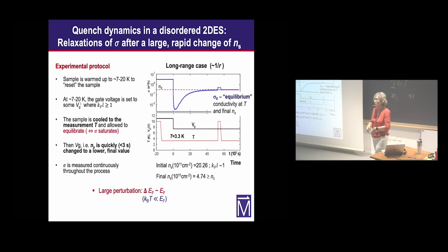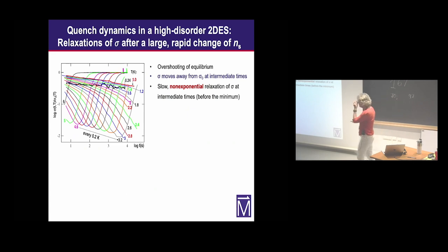Now for the same density, you can repeat these measurements at different temperatures. You get a set of curves, and you put them all in one figure. Each curve corresponds to a different temperature. What we are plotting here is the conductivity for a given temperature normalized by the equilibrium value at that temperature, so that on this logarithmic scale, this 0 corresponds to the equilibrium conductivity for each of these curves. You can see that initially, as I said, the system goes away from this equilibrium value. Then at some later time, it approaches the equilibrium.